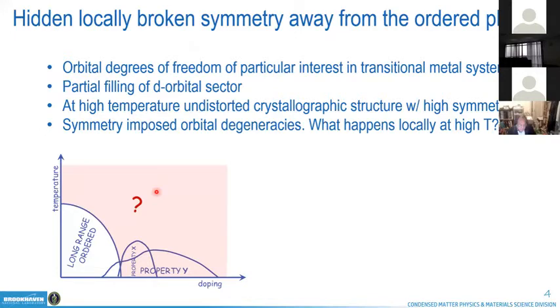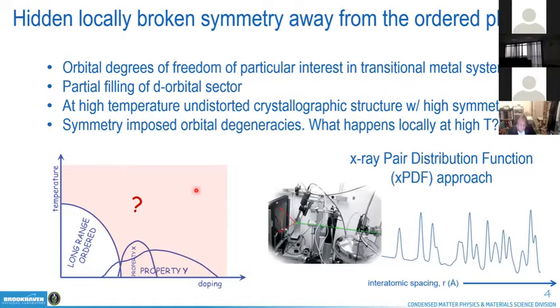And in this specific case, we're interested in transition metal systems that have active orbital degrees of freedom with partial filling of the d orbital sector. And in those systems, in principle, at high temperature, you deal with high crystallographic symmetry, which imposes orbital degeneracies when you look at the systems from the average crystallographic point of view. And so the question that we are asking really is what happens locally at high temperature. And to that effect, we employ a local structural technique, which is X-ray pair distribution function, that does not actually presume periodicity and provides information on atomic structure on different length scales.